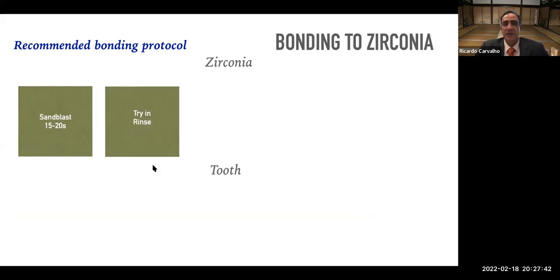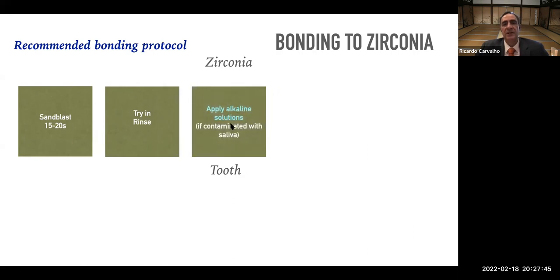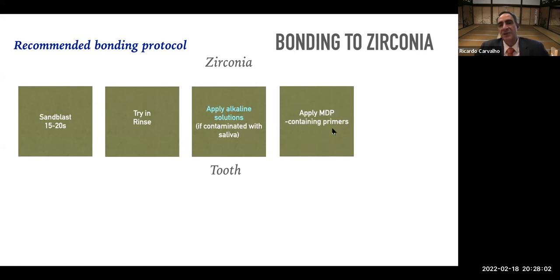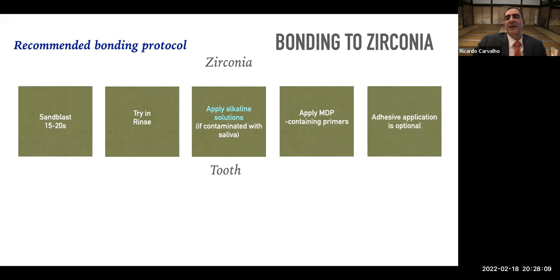Then I can go do the try-in, rinse. There will always be contamination, as we know. That's when I apply my alkaline solutions, if there is contamination with saliva, which is, again, very likely in practice. Then only after I decontaminate the surface, I apply my MDP containing primers or the functional primers, which are specific for zirconia. And then I apply the adhesive, which in the case of zirconia is optional because as we understand, feldspathic and lithium disilicate, I do create porosities. And I need a fluid resin in order to penetrate the porosities and ensure the micromechanical retention.